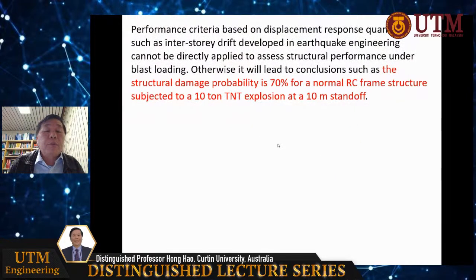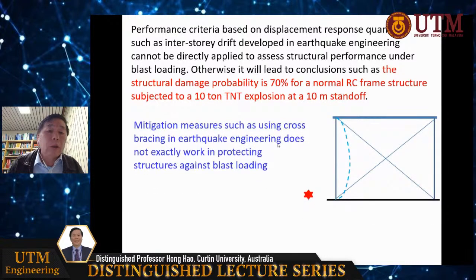So if you use drifts as a criterion to assess the blast effect on building structures, it would be incorrect. There are some research papers that use that. That makes no sense. Some researchers also try to use cross bracing to strengthen the structure against blast loading. That is not effective either, because you don't see the drifts. It works for earthquake, but does not work for structures against blast loading.